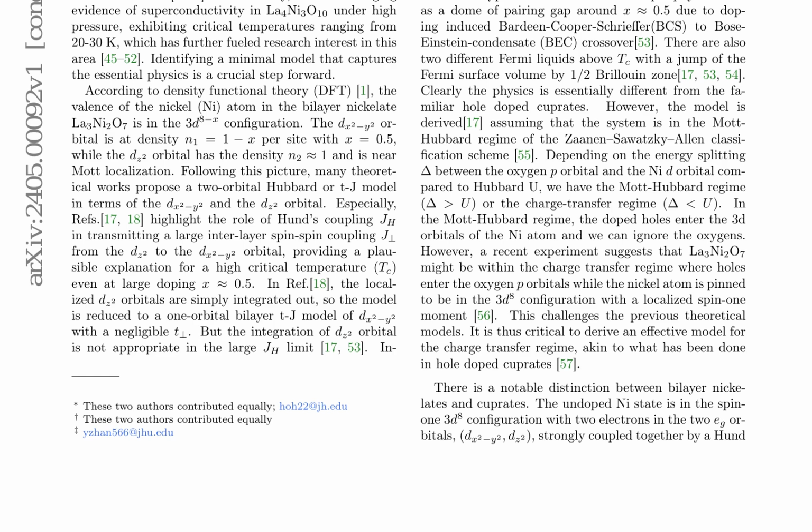Density matrix renormalization group (DMRG) simulations are employed to investigate the doping and pressure dependencies of the spin gap, delta S. The results show a monotonic decrease in the spin gap with increasing t-perpendicular in the large J-perpendicular limit. Furthermore, the paper explores the superconducting dome and its relationship with pressure. Increasing pressure is expected to enhance t_dp,z and thus the J-perpendicular term, initially leading to an increase in Tc. However, when pressure exceeds an optimal value P, the hole prefers to stay in the p_z orbital, resulting in the suppression of pairing and a decrease in Tc.